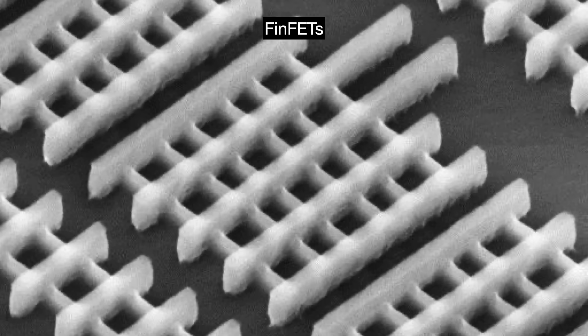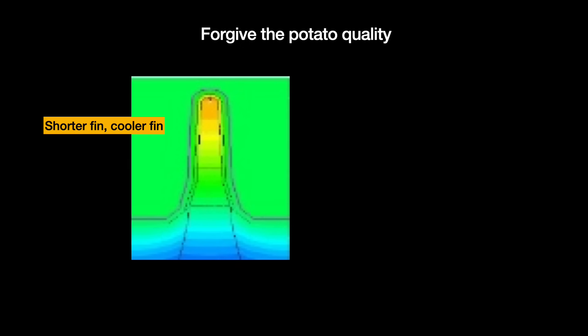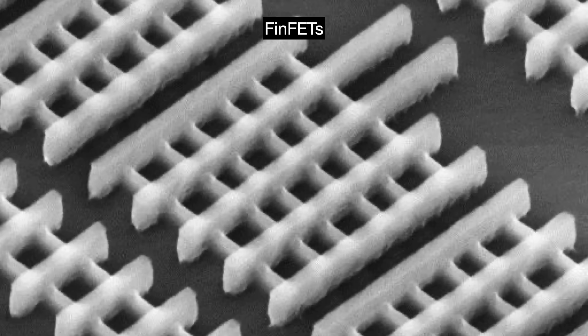Another next-generation transistor device is the widely adopted 3D FinFET, where the channel is turned on its side giving us the eponymous fin. Covering the channel on three sides grants us better control over it. This shape continues the transistor density scaling trend and is at the core of today's leading-edge digital logic devices, but also adds new thermal issues. Dissipating heat generated by FinFETs requires sending it down the fin, which is not so easy. The thermal conductivity of a FinFET at the 14nm node is just 75% that of a planar transistor, and the problem worsens as we scale, making fins taller and skinnier — which means the heat has to travel further to dissipate, and we bunch these transistors together in tight clusters, which only compounds the heating problem.